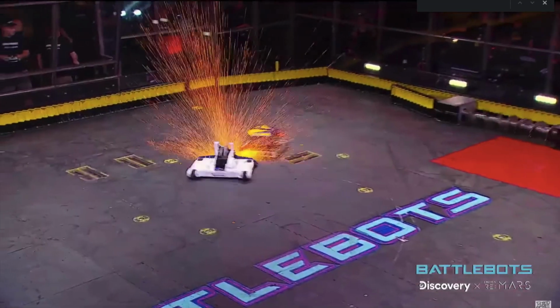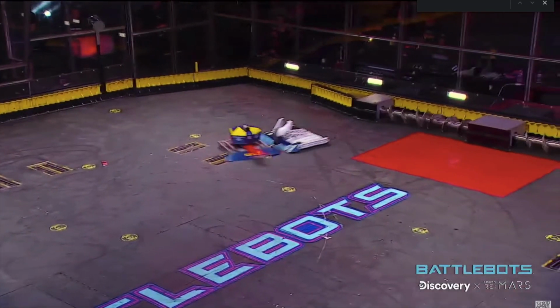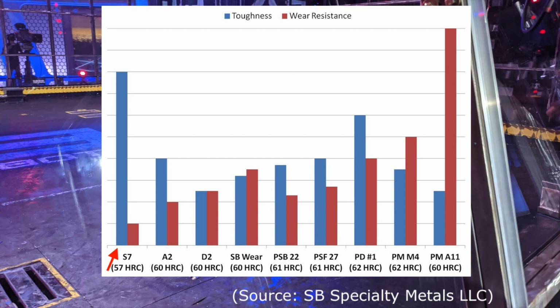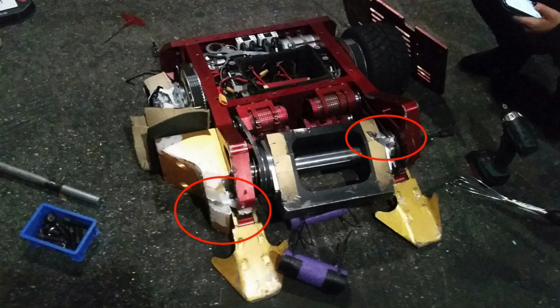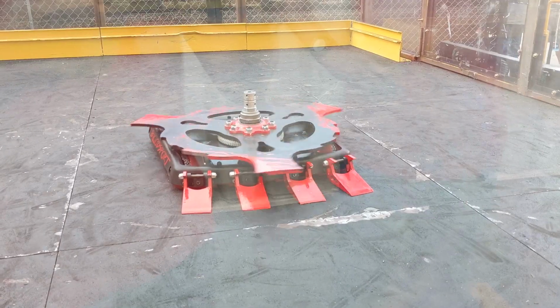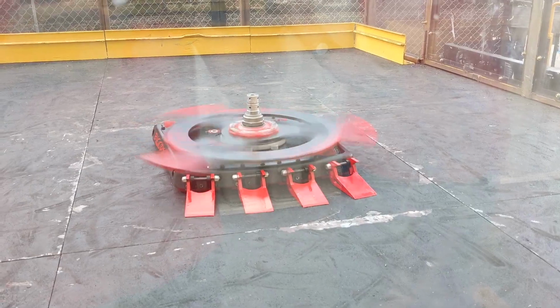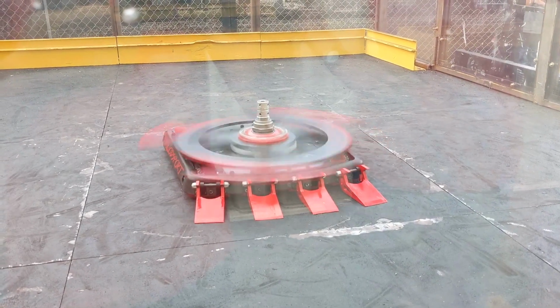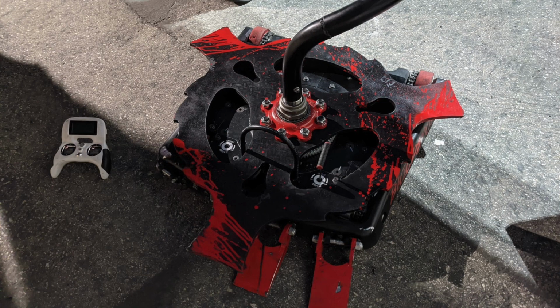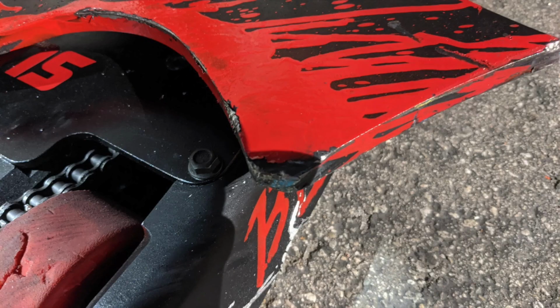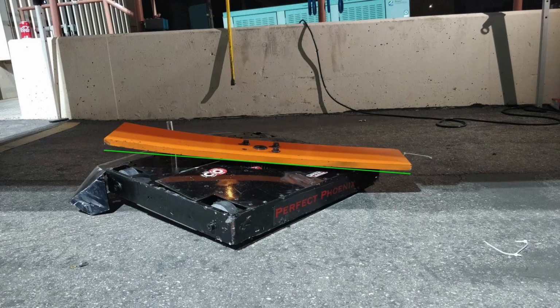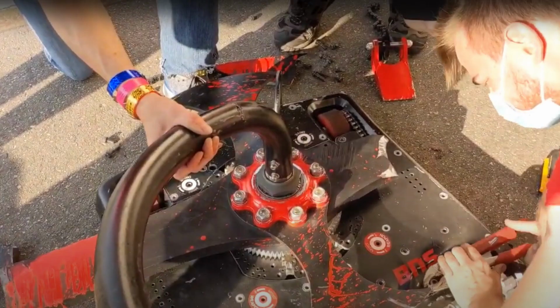Plenty of other bots have broken S7 weapons in the past, but there's a reason it's so common. It's actually one of the more shock-resistant tool steels out there, and the hardness it can reach is beneficial when it comes to digging into armor or other weapons. AR-500 is the other common weapon steel for bots, and the material we made the disc out of. It has a higher fracture toughness and won't shatter like S7, but it's less hard, which means it often dulls quickly. It's also not quite as strong as S7, which means that in a world of theory and spherical cows, AR-500 bends before S7 breaks. As for how that bears out in practice, put a pin in that for now.